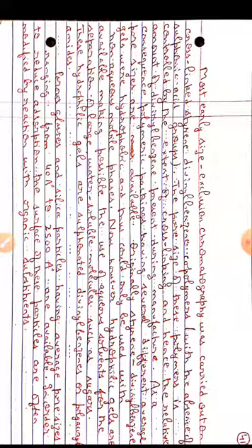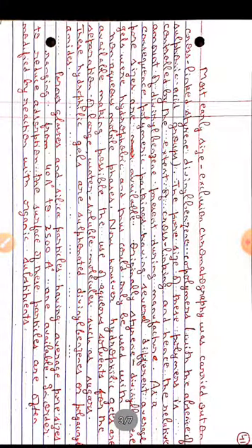Now, however, hydrophilic gels are available, making possible the use of aqueous solvents for the separation of large water-soluble molecules such as sugars. These hydrophilic gels are sulfonated divinyl benzenes or polyacrylamides. Porous glass and silica particles having average pore sizes ranging from 40 angstroms to 2500 angstroms are available. In order to reduce adsorption, the surfaces of these particles are often modified by reaction with organic substituents.